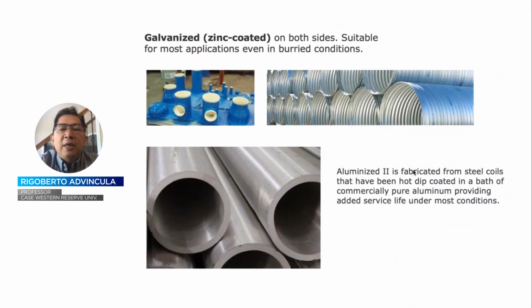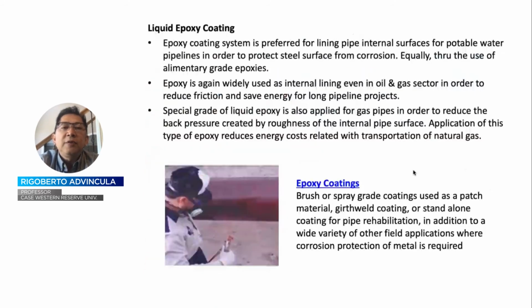So let me give a very short mention here of galvanization. Galvanization essentially is the addition of a sacrificial metal such as zinc that is first oxidized before steel. And you may be familiar with this type of finish. Yet galvanization, aluminization, or other types of protective metal coatings on carbon steel are very environmentally important. That is, rain or shine, or in the absence of polymer coatings, this sacrificial layer then oxidizes to give you another coating based on an oxide, aluminum oxide or metal oxide deposition, that provides that extra layer of protection so that the corrodant does not penetrate the carbon steel, for example.